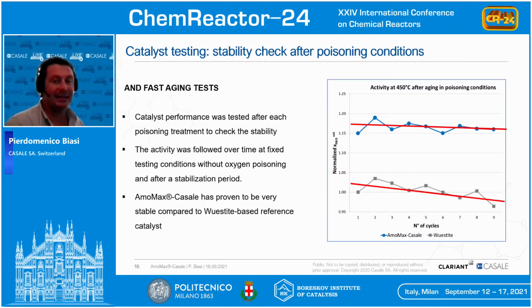But since the ammonia synthesis catalyst lasts for more than 15 years, we also needed to find an aging procedure that was representative of the aging in the real plant. So what we did was work with Clariant, understanding the performance of the plants. We established a procedure for faster deactivation, and we did several cycles representative of several months of operation in real plants to understand how much faster the deactivation was compared to the wüstite-type catalyst and the magnetite catalyst. And we saw that the new AmoMax-Casale catalyst was more performing and more stable compared to the classical catalyst, because here you can see that the slope is lower compared to the classical wüstite-type.